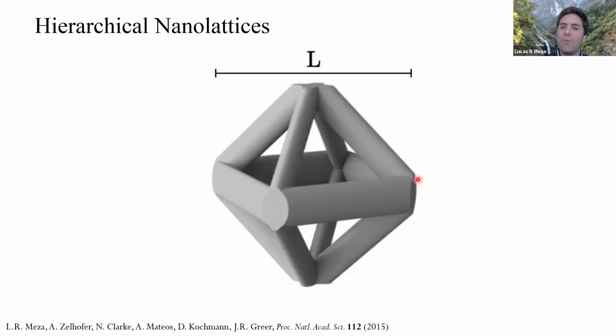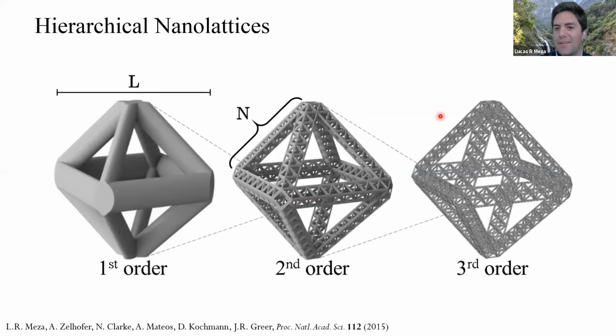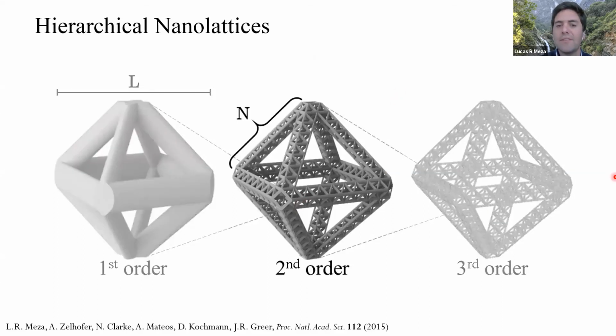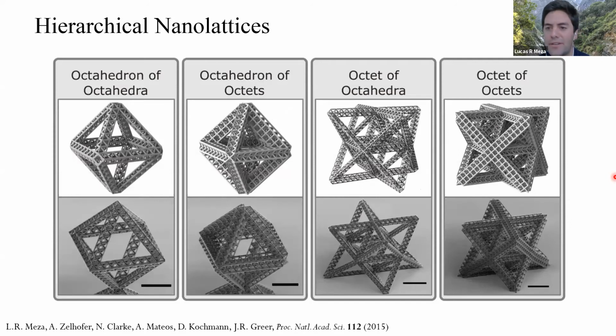This idea we took a single order lattice, and made lattices out of those, lattices out of those. You can repeat this ad infinitum, and combine these across a whole bunch of different types of architectures, so it's a fairly general method. These at the top are CAD images, these at the bottom are SEM images, all the scale bars there are 20 microns. We're getting the same sort of size as the monolithic nanolattices, but an increased complexity in the architecture.